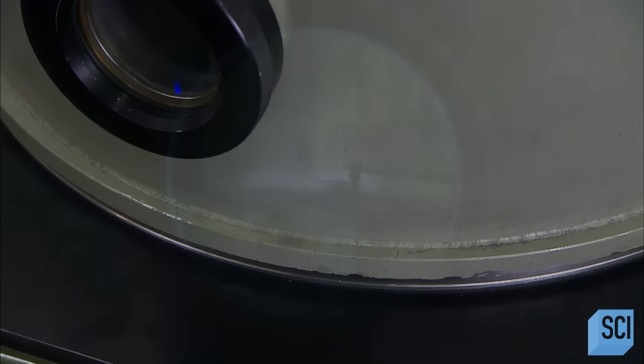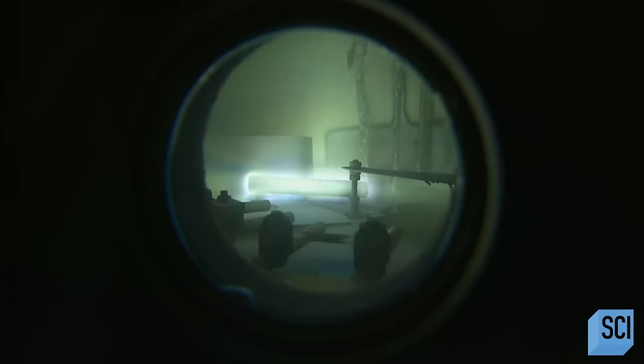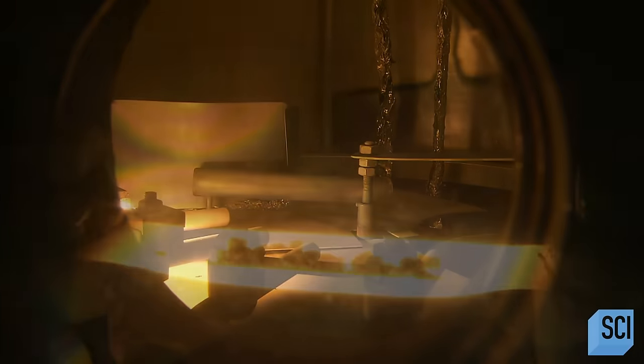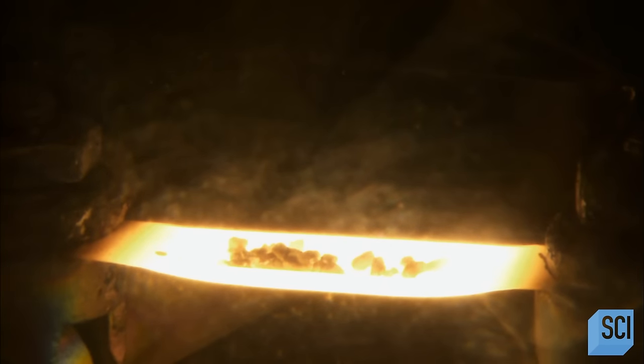They activate a six thousand volt electrode. This sparks a glowing discharge of ions onto the now rotating glass disc. These ions blast any lingering contaminants from the glass to give it a serious cleaning.